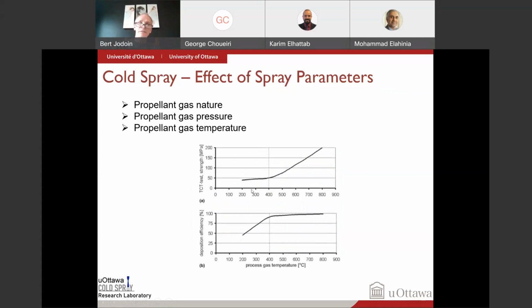If you look here at the same effect, if you look at the gas temperature on the tensile properties, as you increase the gas temperature, the velocity of the particle increases and they're going to bond much better. Same thing with the deposition efficiency. At one point now you go fast enough that most of them will stick.